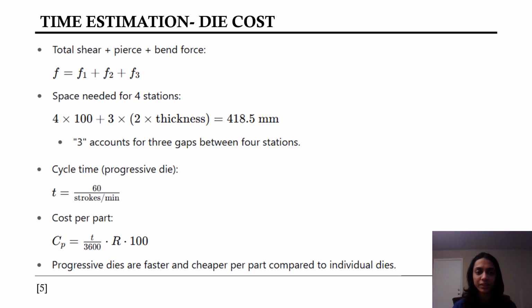So let's wrap up the time estimation by discussing progressive dies, which combine multiple operations like shearing, piercing, and bending into a single automated process. So the total force required here is the sum of the forces of all the operations in the die. Now, if we are designing a progressive die, say for 4 stations, we also need to allocate the physical space. So that is calculated by 4 into 100 mm plus 3 into 2 times the thickness. So 3 is the gap between the stations and the formula gives us a total strip length of like 418.5 in this case. This is critical when designing strip layout and estimating blank feed per stroke.